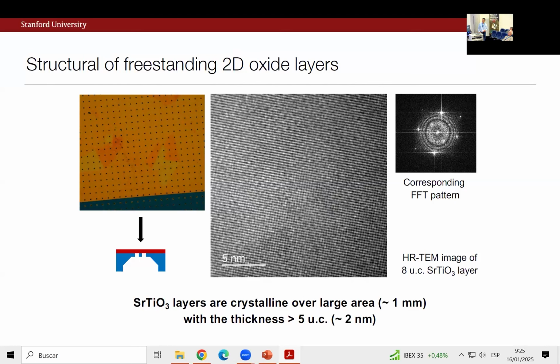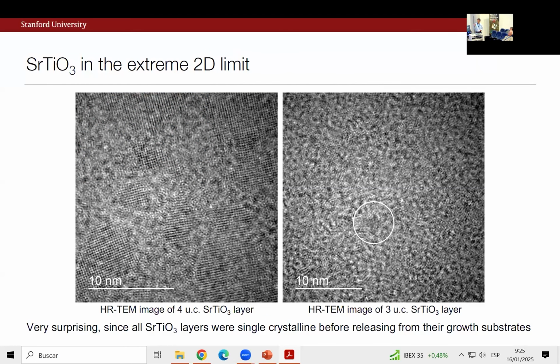What was very surprising to us was that if you go just a little bit thinner than that, there was a dramatic change in that image. This is just going from 5 to 4-unit cells of strontium titanate. You can see already a very dramatic change where you can see patches of crystalline domains, lots of strange things in between. And going from 4 to 3-unit cells, you can see the length scale for crystalline coherence is just rapidly collapsing down.